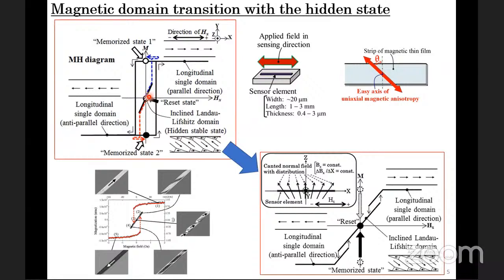We call this state a hidden stable state. Stable means that this state has a lower energy compared with the dipole state. This hidden stable state exists in the condition when the magnetic easy axis lies in the direction almost 70 degrees against the width direction of the element.